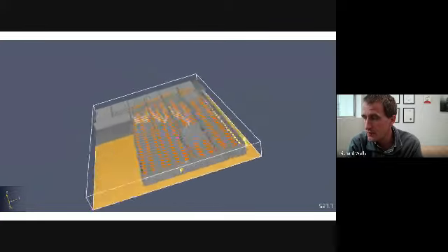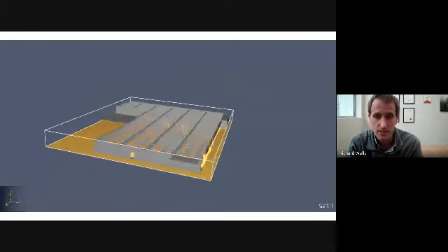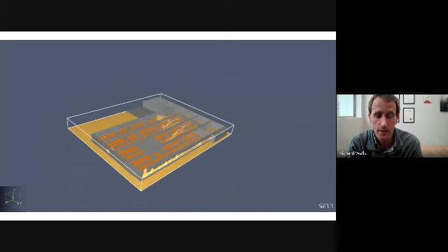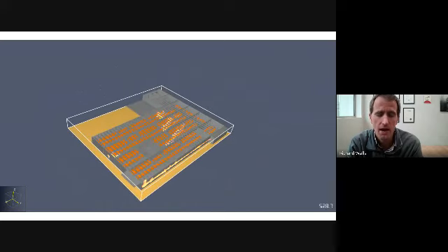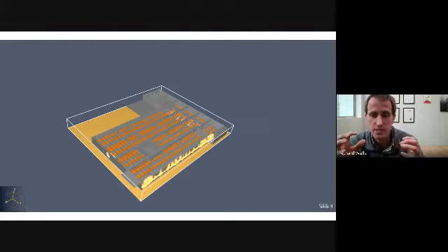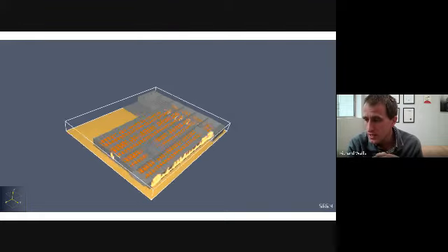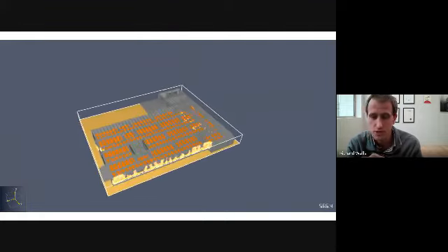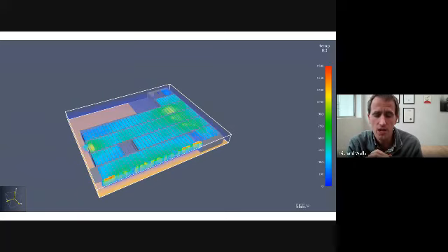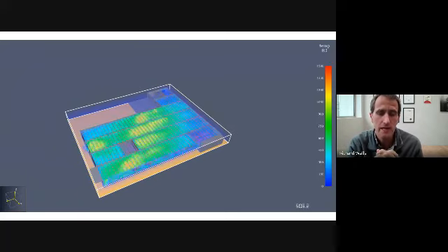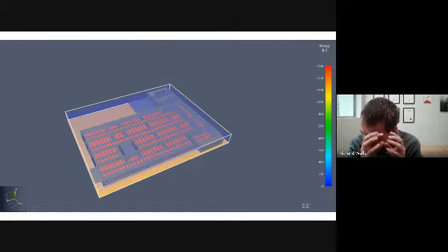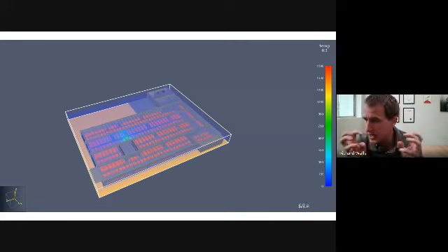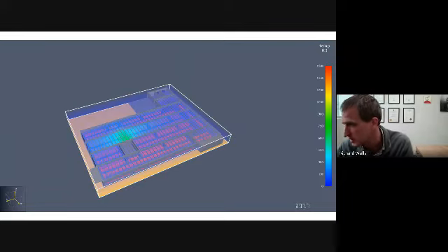Where it does become problematic is where you have high density concretes, very dense matrices, because then the steam can't escape. There are ways if you have higher risk concrete. For instance, you put polypropylene fibers in, tiny little plastic fibers in the concrete, and then when the fire occurs, they melt and allow the steam to escape. So it's actually one way of improving the fire resistance of your concrete without doing too much.